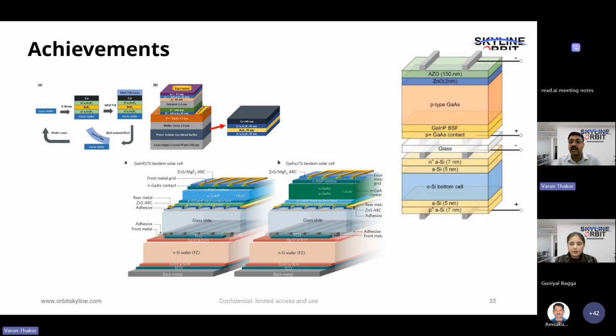So imagine what all we can achieve. We can achieve growth on glass, which for any engineer is like the gold standard, because glass we cannot use to grow directly. We must grow on a silicon or gallium arsenide crystalline sample because they are epitaxially matched and they are clean room compatible materials. Clean room means MBE compatible, but glass is cheap. So if we can grow on these crystalline films and then transfer them onto glass, then we can make cheap solar cells. So this has been achieved now. This I have taken from a very highly cited paper. So this has been achieved already.